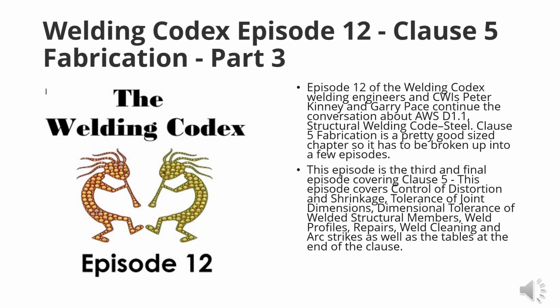And then we've got 5.21.4.2 correction: root openings greater than those allowed in 5.21.4.1, but not greater than twice the thickness of the thinner part, or 3/4 of an inch, whichever is less, may be corrected by welding to acceptable dimensions prior to joining the parts by welding. So what's that telling us, Pete? You spread some butter on it. Yep, you just build it up. You get your good welder, and you get a stack of filler material, and you just build it up and grind it and clean it and follow all the appropriate rules. Keep people in the loop on what you're doing. Build that thing up. Add yourself a little bit of material, clean it up, and go from there.